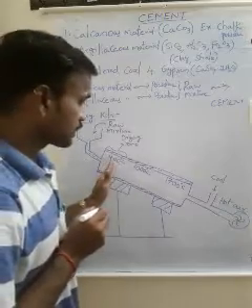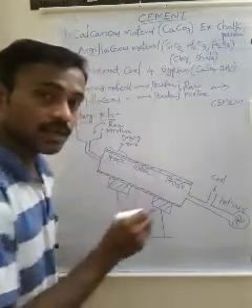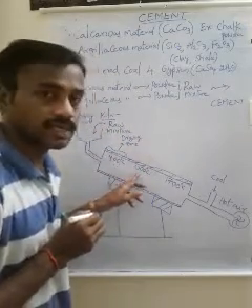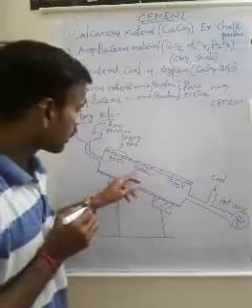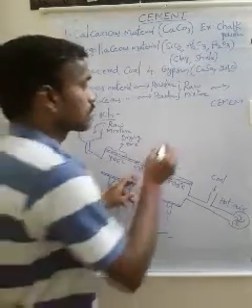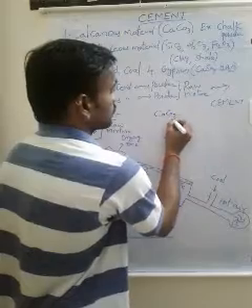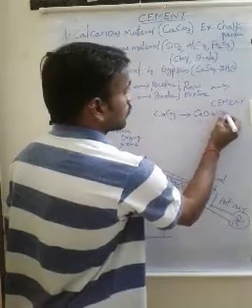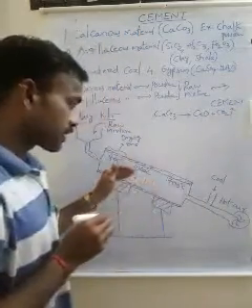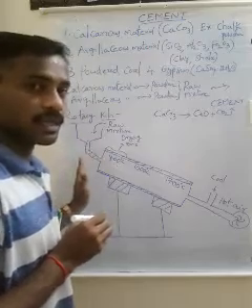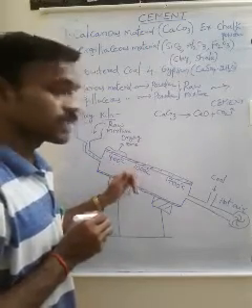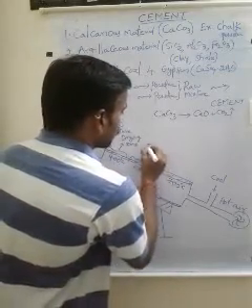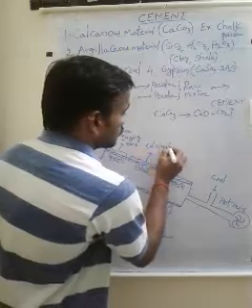Next, this dry mixture enters the central part of the kiln. In the central part, temperature is about 1000 degrees centigrade. At this temperature, one of the raw materials, calcareous material, is decomposed. Calcium carbonate decomposes to calcium oxide and carbon dioxide gas. That carbon dioxide gas escapes out through the chimney. Here in this zone, calcareous material is decomposed, so this zone is called the calcination zone.